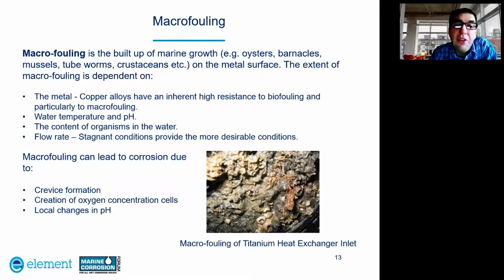So the stagnant conditions provide the most desirable conditions for the growth of these marine bodies. So macrofouling can lead to corrosion due to crevice formation and also due to creation of oxygen concentration cells and also due to local changes in pH. So the photograph here shows macrofouling on a titanium heat exchanger inlet.